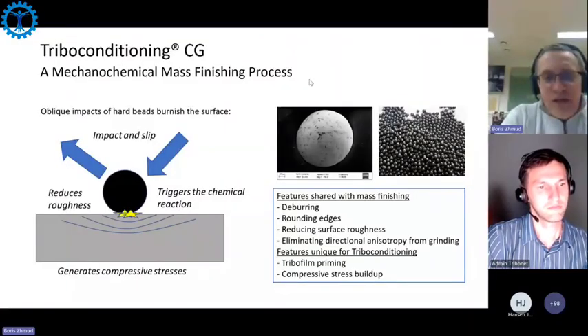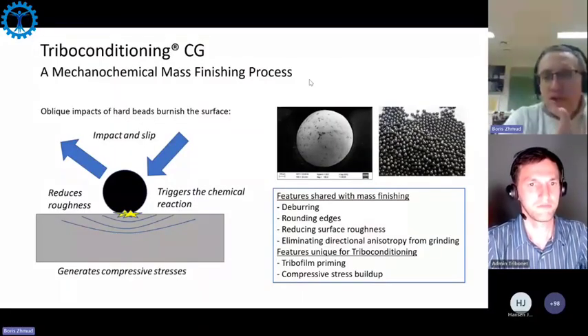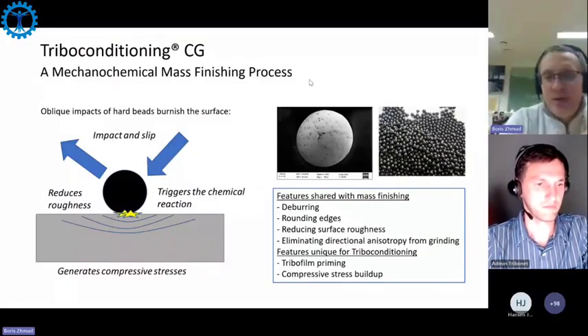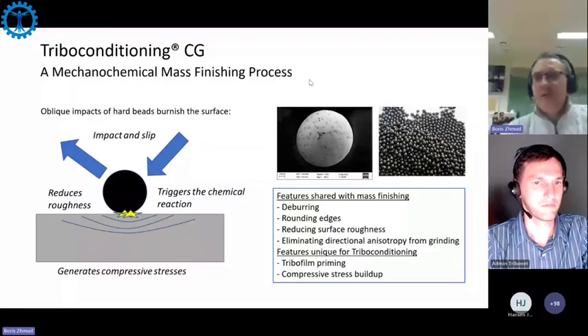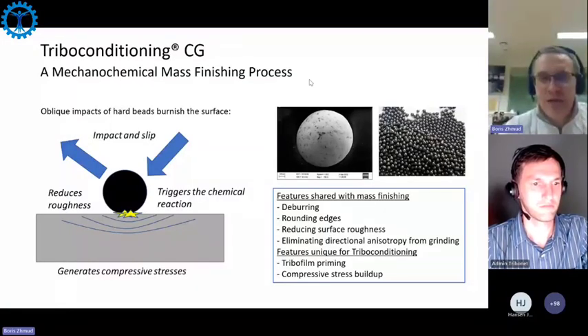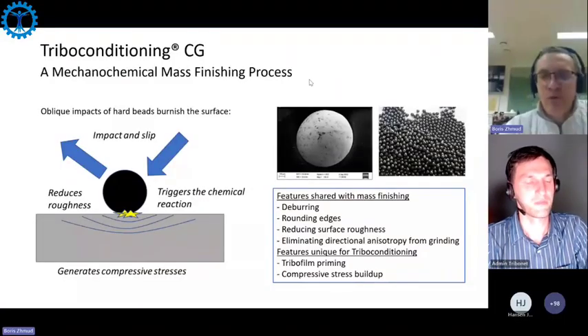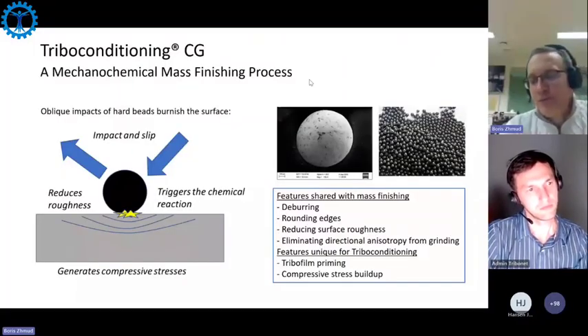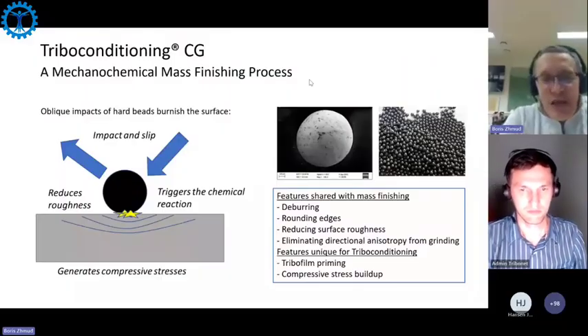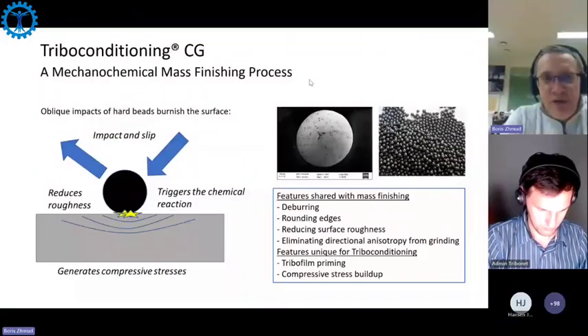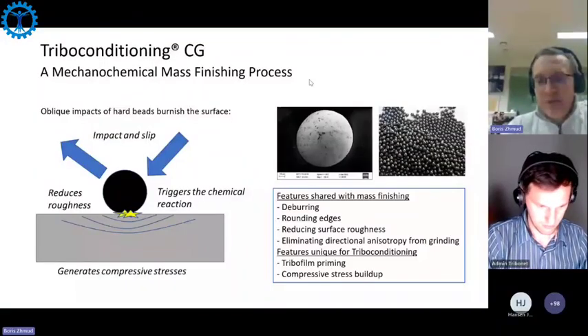Yeah, so, and then compressive stresses. I mean, conventional abrasive processes are very often used to remove compressive stresses from the grinding operation, because grinding operation, gear grinding, also produce compressive stresses. But in mechano-chemical finishing, we actually generate compressive stresses, but we just have different tensor of compressive stresses, which would improve performance in terms, for example, of rolling fatigue, improve performance in terms of micro-pitting. Yeah, so this type of really differences we see from mechano-chemical process compared to conventional mechanical process.